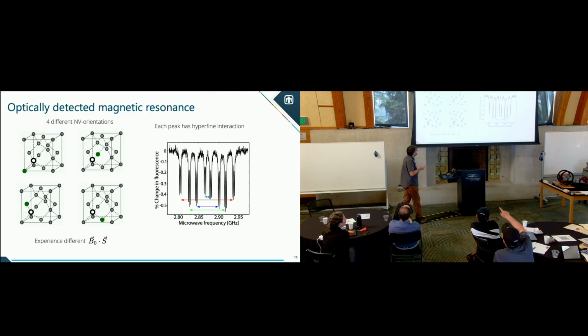Each of these 4? That's because of the contrast of this screen, and I have to apologize. So this little guy here is green, that's your nitrogen. This is a vacancy, and your nitrogen's there. And then this one is your vacancy, nitrogen there, vacancy there. So you have 4 different orientations of nitrogen relative to the vacancy within the diamond crystal lattice, right? Tetrahedron. I'll change that to yellow next time.